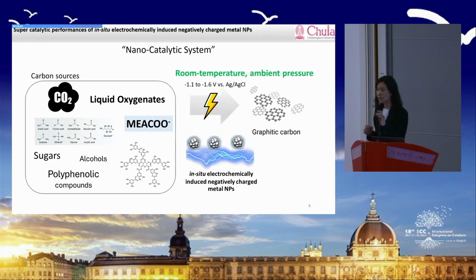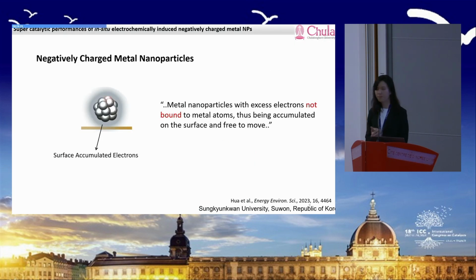This is the system that I'm talking about. The catalysts are made in situ, we call it electrochemically induced. I use a little bit of electricity to create these negatively charged metal nanoparticles. They have a super catalytic power that is able to reduce all those carbon sources into graphitic carbon products, and a lot of them. You can ask me later how much I get. And all at room temperature and ambient pressure.